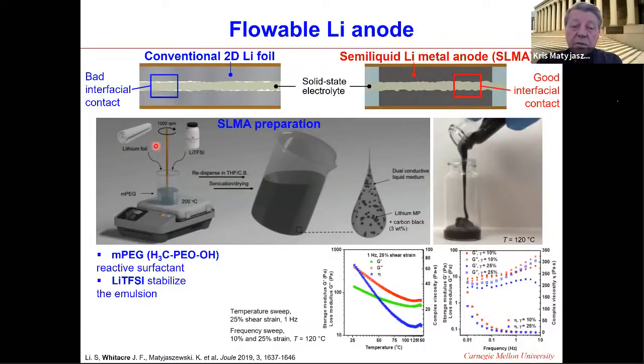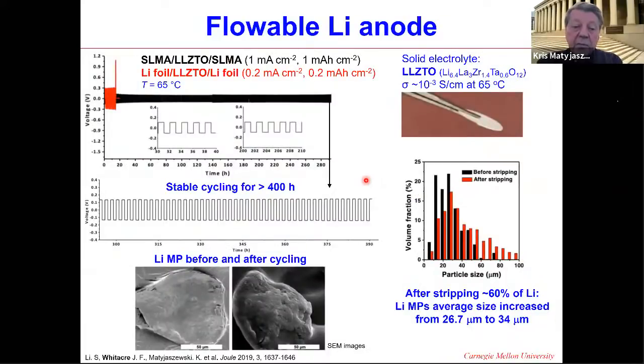We did that by using just lithium foil at higher temperature with mono-methylated and monohydroxy pegylated structures, and then adding a little bit of carbon black for better conductivity, and we developed this flowable lithium anode. It has very good properties. You could see stable cycling over 400 hours, with these cycling back and forth systems. The size of the particles during the cycling process slightly increases from 27 to 34, more or less, after stripping 60% of lithium. And we are using here the solid electrolyte based on lithium, lanthanum, zirconium, and tantalum, so LLZTO.